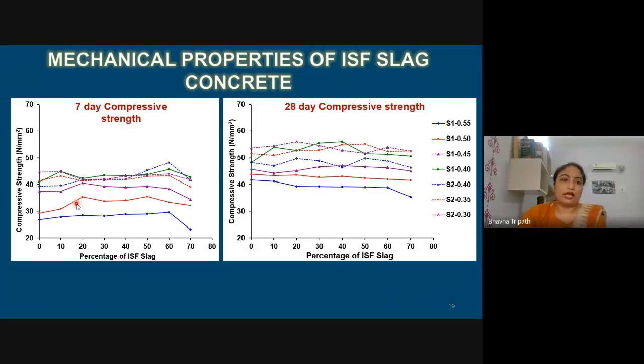The reason goes back to the morphology. As I have already discussed, the morphology of ISF slag was irregular, and the particle size range, maximum particles were falling between 2.36 mm to 0.6 mm. Maximum particle size were of that range, and that range particles had irregularities in their surface. There were cavities, and it is obvious that some of the water would have been entrapped in those cavities, and this has resulted in lowering the effective water cement ratio. And that is why we are seeing a superficial growth in strength in earlier days, which stabilizes gradually.